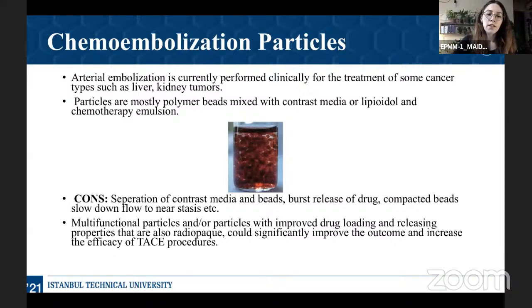But the particles that are used are, as I mentioned before, mostly polymer beads mixed with X-ray contrast media. There are several disadvantages to these particles. The contrast media and the beads can separate during the administration. Also, there's a rapid and burst drug release response to these particles. Also, some particles, mostly hydrogels, can be compacted during the administration.